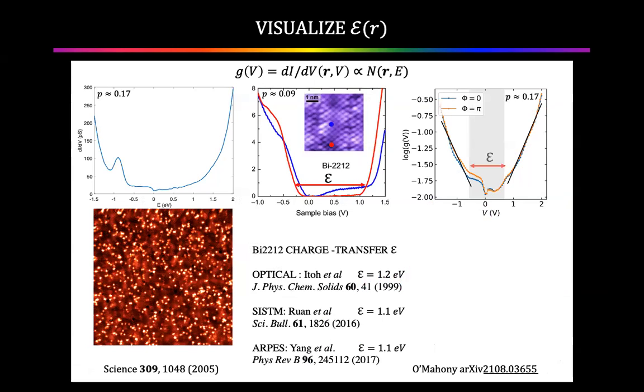All right, next thing is the energy gap. In single electron tunneling spectroscopy, you can see the energy separation between a high density of states span below the chemical potential and a high density of states span above the chemical potential. Actually, all STM people have known that for 20 or 30 years. Not a big surprise. Ruan showed a few years ago in this very nice paper that one can essentially measure that energy gap between the top of the lower band and the bottom of the upper band as a function of location, which is a great idea. Now, you can quibble about whether this is really the charge transfer energy in the three-band Hamiltonian. At present, I don't know.